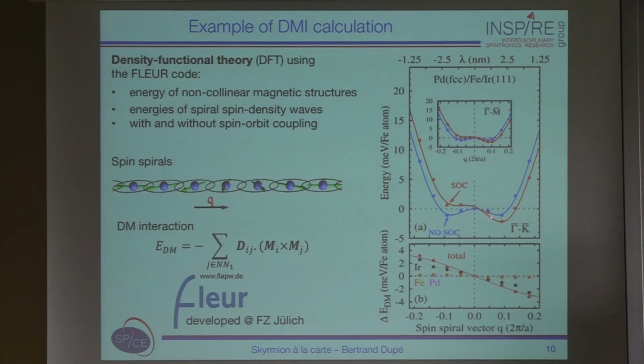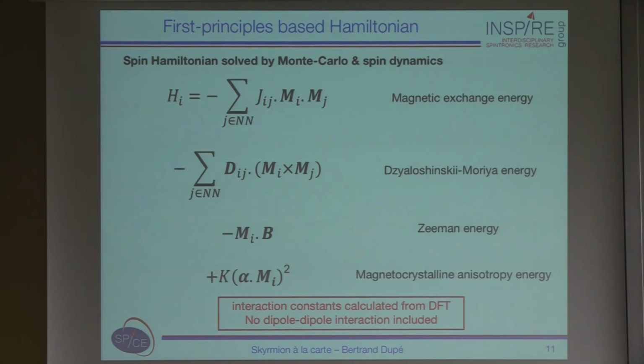So here with this calculation we actually have everything. You have the magnetocrystalline anisotropy, the exchange, and the DMI. So you are ready to set up your effective Hamiltonian, which contains all the ingredients. You plug on top of it the magnetic field, and then you can play with this with Monte Carlo or spin dynamics, depending on what you want to do.